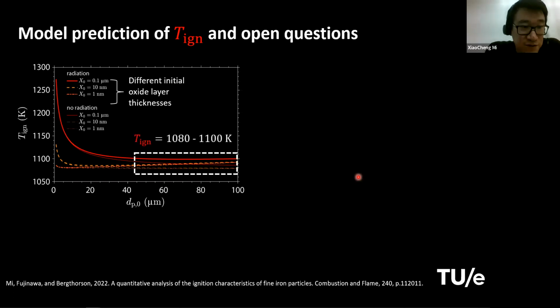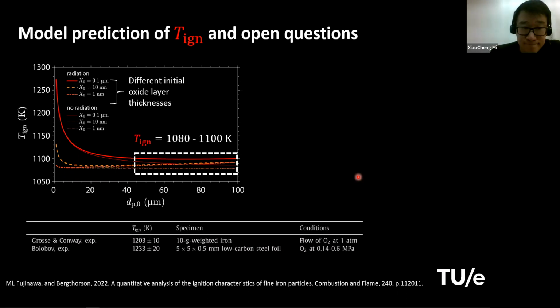So for large enough particles, this ignition temperature is estimated by this model to be somewhere between 1080 and 1100 K, right? And right now, the only experimental value we can compare with is not for iron particles, but for iron foils, or a small piece of iron held by some supporter. And they determine this ignition temperature with a similar definition as we use here. And they show that this temperature is not too far away. I think it is less than 10% different. But since they are holding these samples with solid frames, they also experience some conductive heat loss, and that can increase the required ignition temperature.